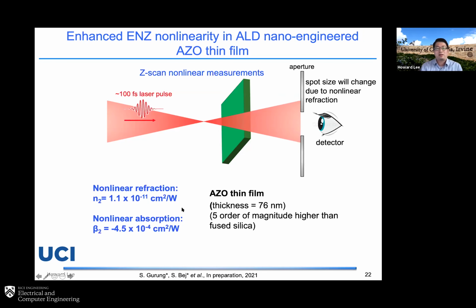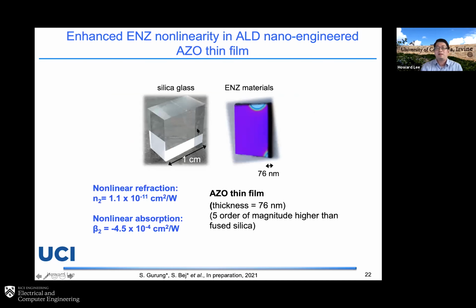I tried to skip some of the details just to give you the values we're able to measure. For example, for the AZO material with 76 nanometer thickness, we got these n2 and beta values, which are already five orders of magnitude higher than fused silica glass. What that means is that if you need silica glass with 1 centimeter of material to get a similar phase shift using this femtosecond laser power, then using an ENZ material, you may only need maybe 100 nanometers or less to introduce a similar phase shift with the same power we're using here. So this is why you can enhance the nonlinearity by a couple of orders of magnitude using ENZ material.